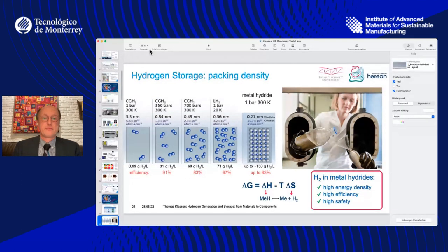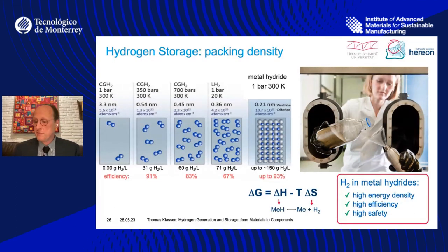If you compress that, sorry, that was my fault. So if you compress that to 350 bars, you can bring the molecules closer together. You reach already 31 grams of hydrogen per liter. However, you have to spend some energy for compression. So the efficiency is 91%, then you lose 9% of the energy for compression. You can double the pressure to 700 bars, press it even further, get up to 60 grams of hydrogen per liter, and you spend about 17% of the energy content.